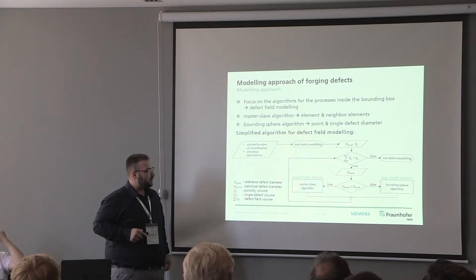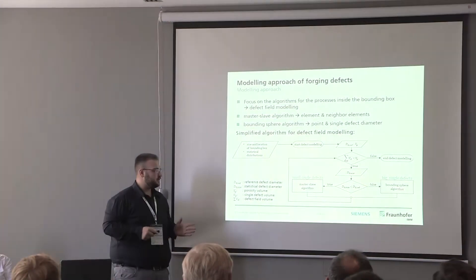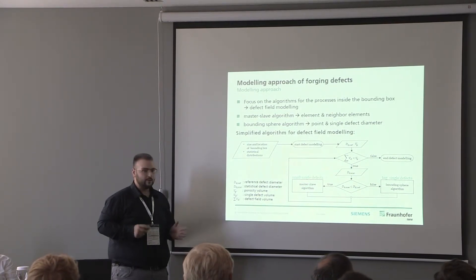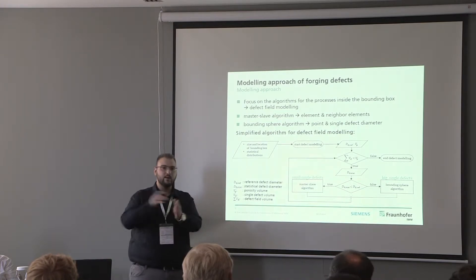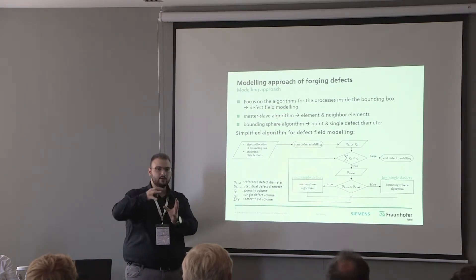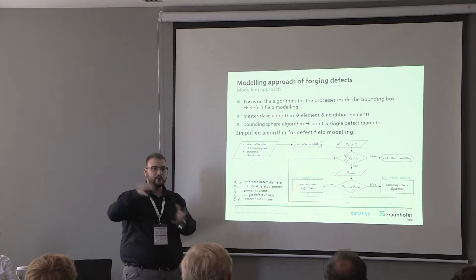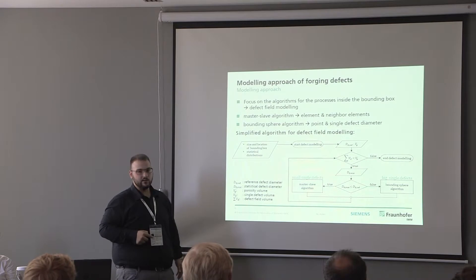I developed a master-slave algorithm to set up small defects, using an element and its neighbors to set up a defect. There is also another method — the bounding sphere algorithm — where I use a point and a diameter to set up the defect. The bounding sphere algorithm is for big defects and the master-slave algorithm is for small defects.